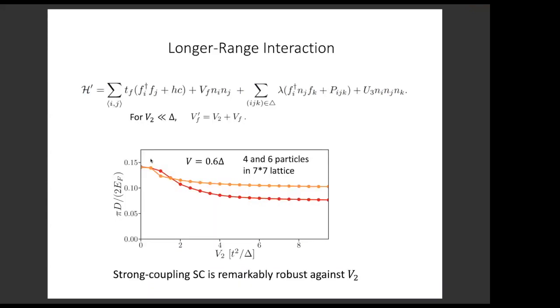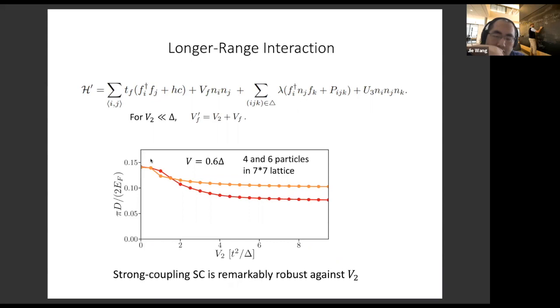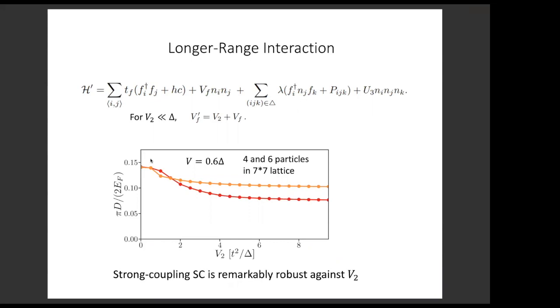Okay, so here I also want to say that if we include the longer range interactions, so if the longer range interactions V2 or V3, etc., are small compared to the band gap, then the leading effect is that they can be directly added to the effective model, the effective Hamiltonian for doped electrons. And what we found is that the superconducting state is actually remarkably robust against the longer range interactions. So this comes from the exact diagonalization study. Okay, next slide.